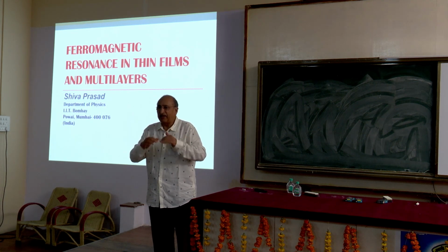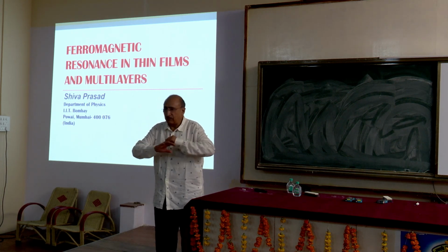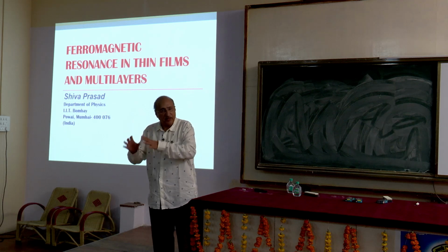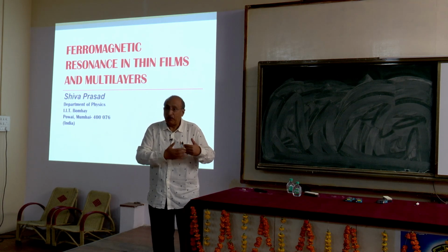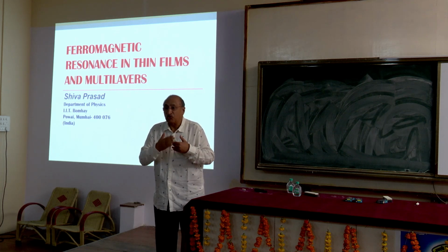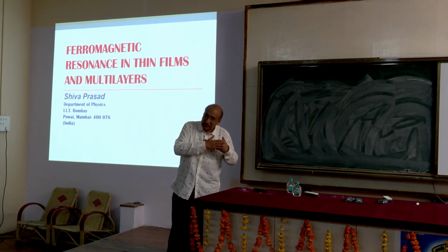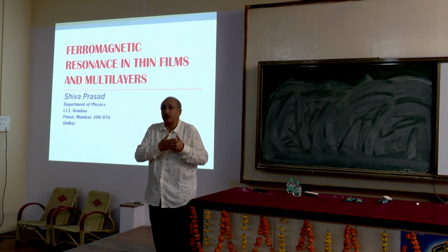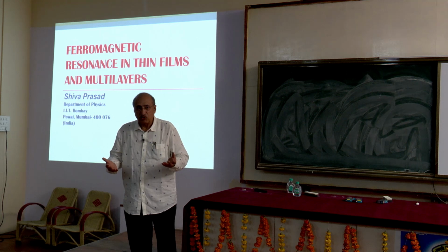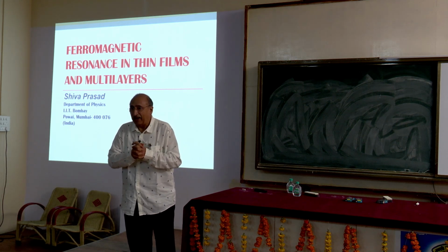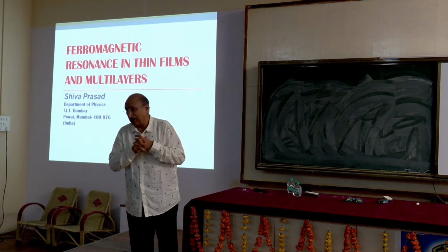Then we say that in 3D transition metals, orbital angular momentum is quenched. It means we take L equal to 0. We assume that J is contributed only by S, the spin. Then you get a different moment. But when you actually evaluate experimentally, you get a value different from this. The reason is that you have neither a situation where orbital angular momentum is completely quenched, nor one where it's not yet quenched. It's a partially quenched system, and that's why you get magnetic moment values quite different from the theoretical value.